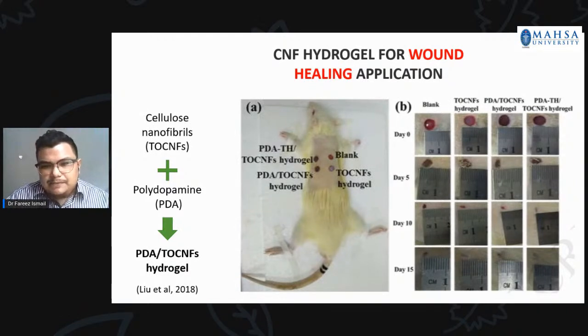And this can be caused by bacterial infection, especially during the first 48 to 70 hours, and that can contribute to non-healing or chronic wounds. And nanocellulose is not only efficient as a physical barrier against the external infection, but it can also form a porous network structure in the material scaffold, to deliver the antibiotics or other medication into the wound. For example, in this study, they produced cellulose nanofibrils by means of TEMPO-mediated oxidation method.